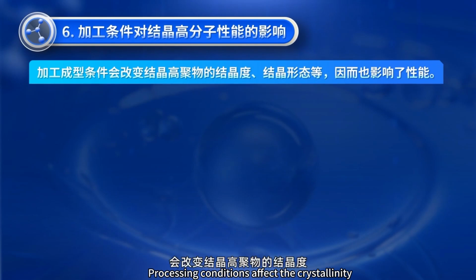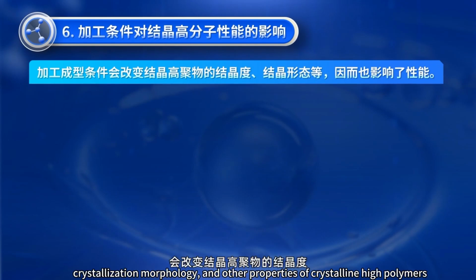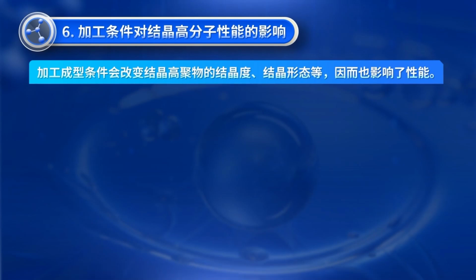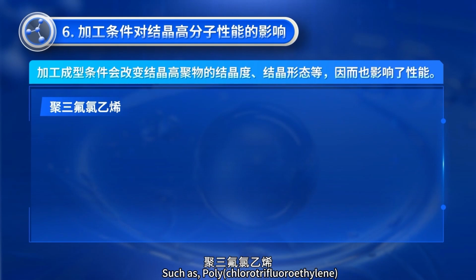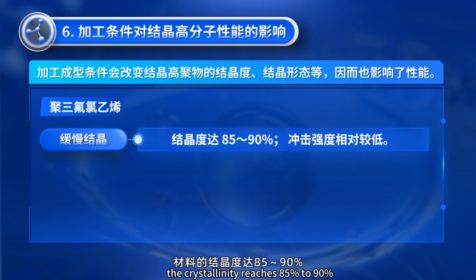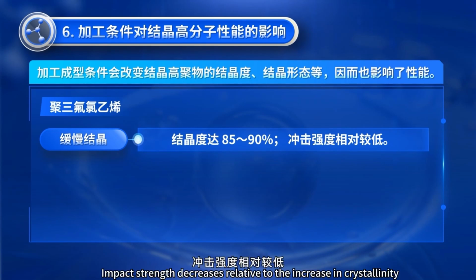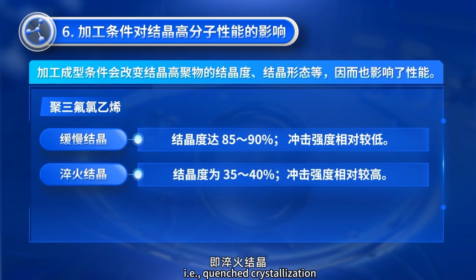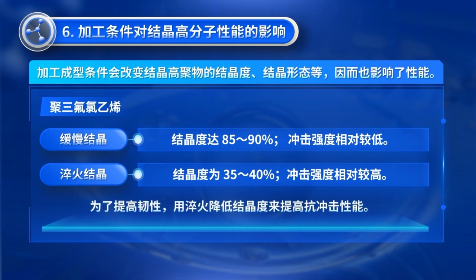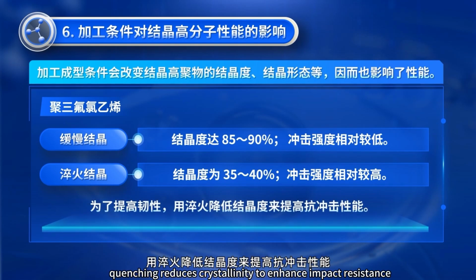Processing conditions affect the crystallinity, crystallization morphology, and other properties of crystalline high polymers, thus affecting their performance, such as polychlorotrifluoroethylene. If cooled slowly, the crystallinity reaches 85% to 90%. Impact strength decreases relative to the increase in crystallinity. If cooled quickly, that is, quenched crystallization, crystallinity reaches 35% to 40%. Impact strength is relatively high. To improve toughness, quenching reduces crystallinity to enhance impact resistance.